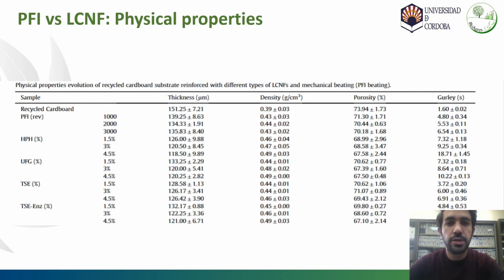The physical properties were also analyzed, and we see how the thickness decreased with the increasing intensity of the mechanical refining and the nanofiber content. In addition, density increased, porosity decreased, and Gurley porosity increased. This is due to the fiber bonding produced by both technologies, especially the interaction between the cellulose nanofiber and the filling of the voids in the paper matrix by the nanocellulose fibers.